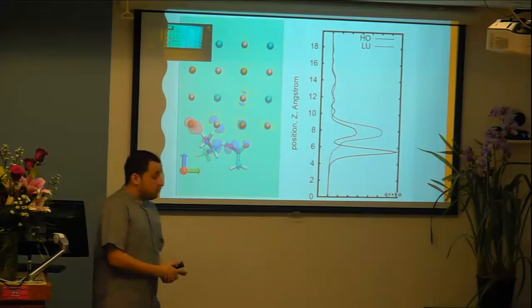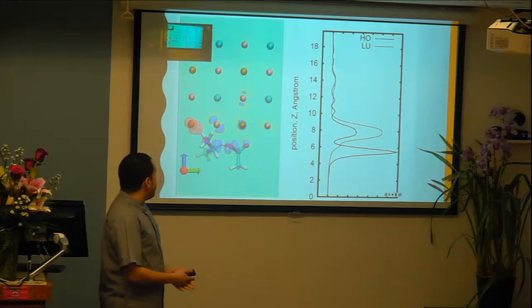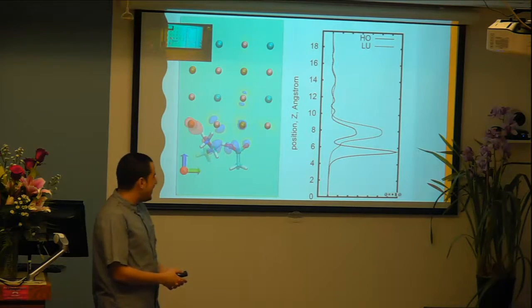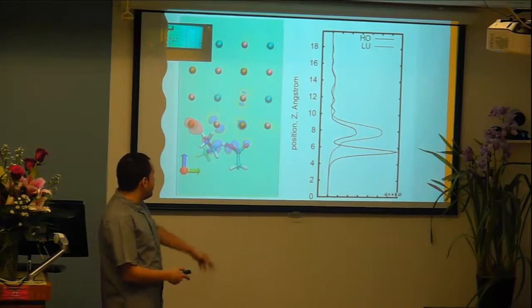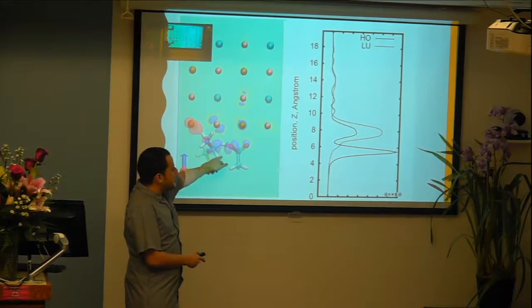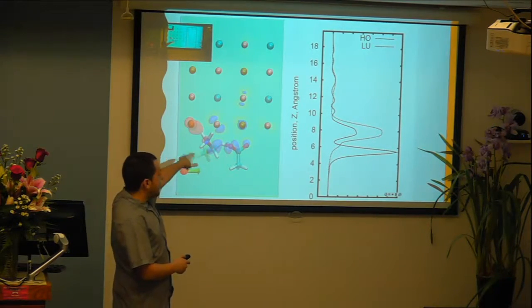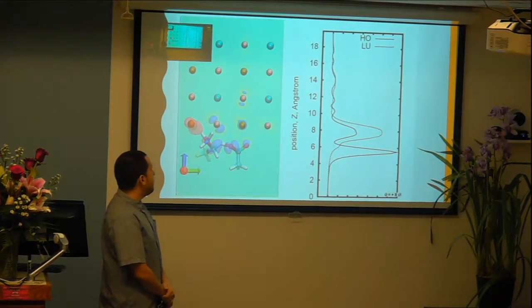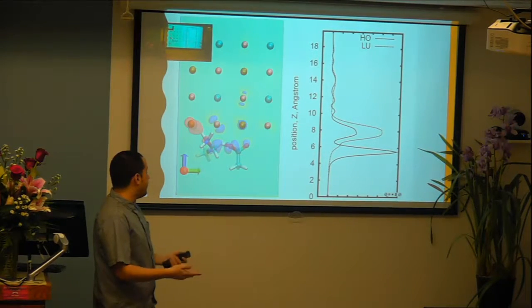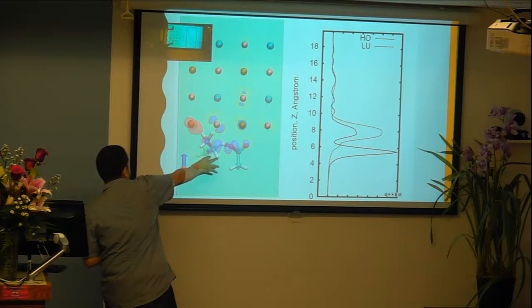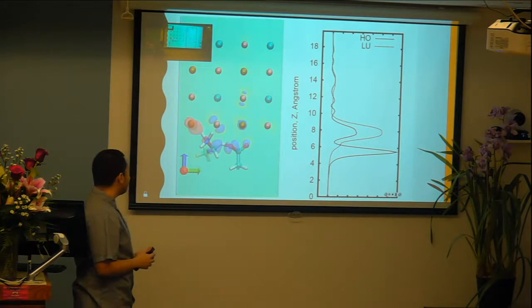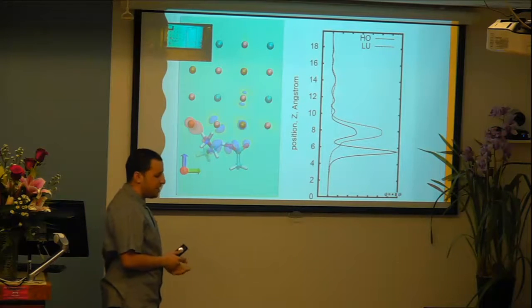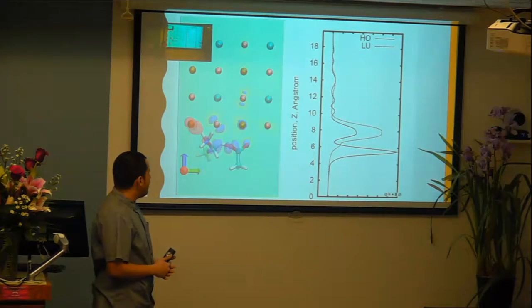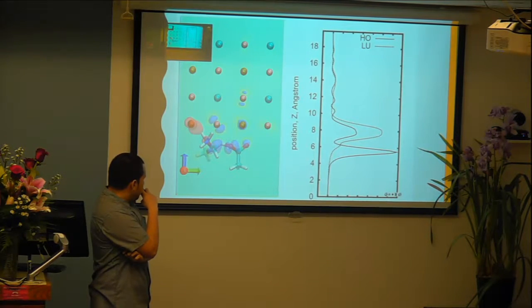And whenever it comes to comparing our HOMO and LUMO gaps, apparently Landon and I like to use the same type of color coding. So blue, in this case, is my HOMO, and the red is my LUMO. So we see most of the HOMO density coming from the ligands, and what's interesting is that during the simulation, our ligands ended up bonding to each other, which is kind of hard for me to explain.